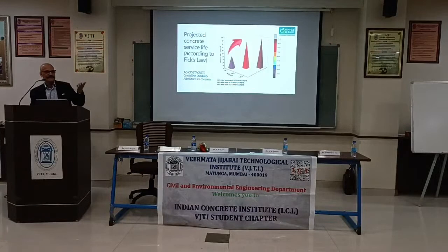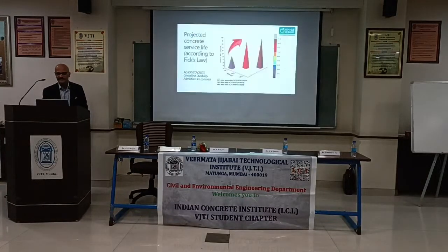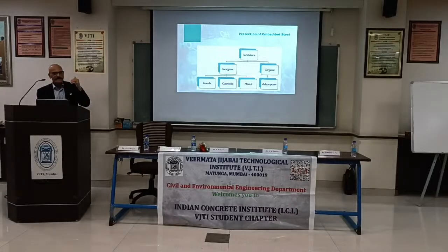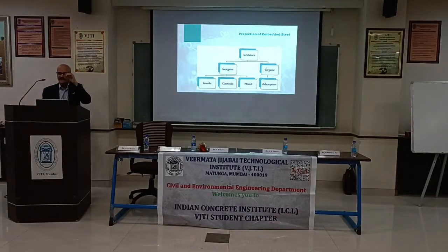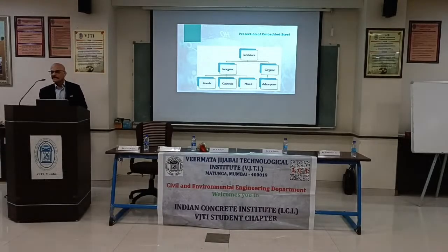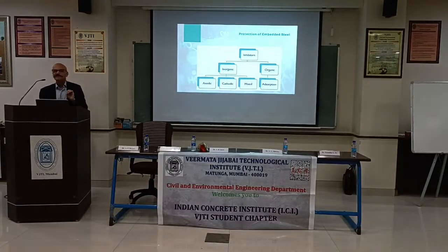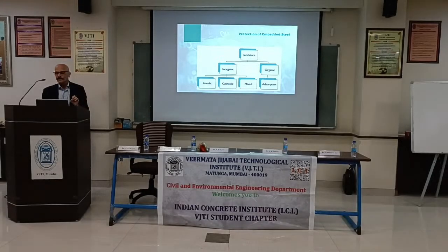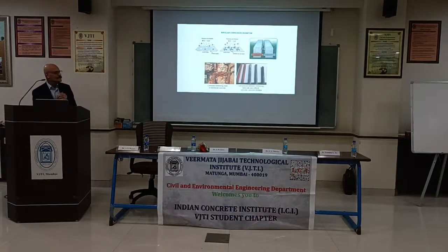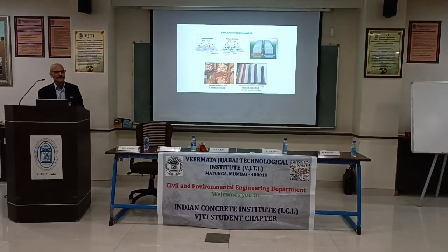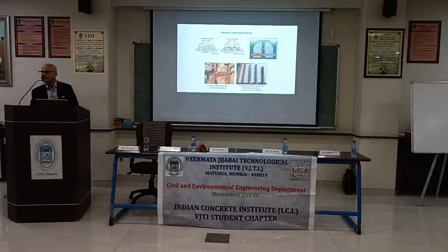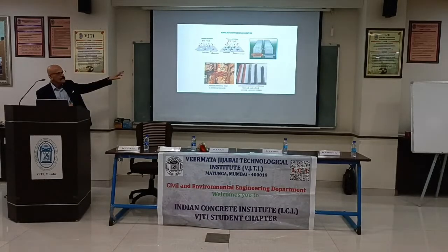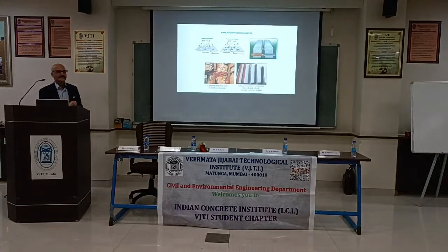And of course, then there are conditions where the structure is put up and there are ice provisions. When you shoot out the problems within the concrete, there is something called steel also sitting inside. And steel corrosion is the biggest problem. So to control the corrosion of concrete, there are some additives which are developed. To the extreme right of your screen, you can see that if you are adding bipolar corrosion inhibitors in the concrete, these are liquids added into the concrete, which form a sort of passive media over that rebar, and then the rusting of the steel doesn't take place. So this again enhances the durability.